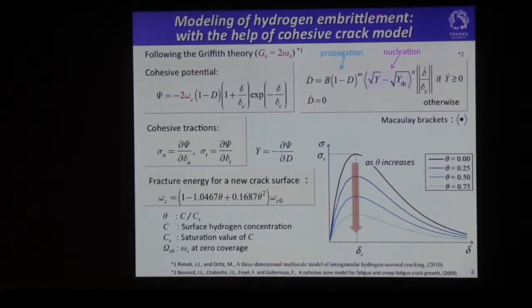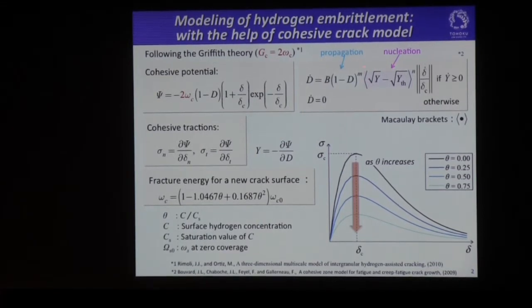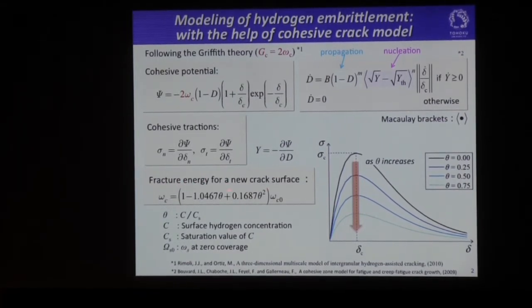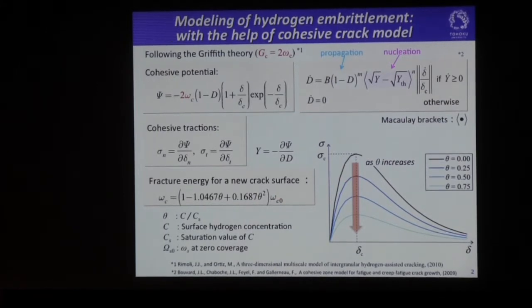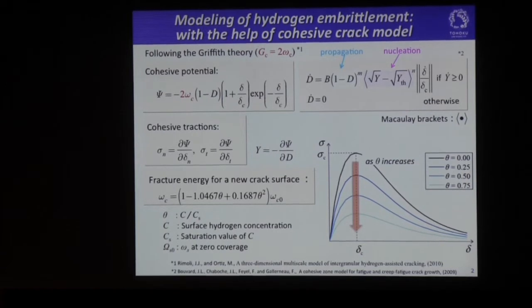This slide shows the modeling of the hydrogen embrittlement with the help of the cohesive crack model. Following the Griffith theory, I introduced the cohesive potential of this form. With this cohesive potential, we could derive the cohesive traction like this as a thermodynamic force. Here D is the damage parameter, whose evolution equation is given here, which represents the nucleation and propagation of the cracks. At the same time, this potential is multiplied by the fracture energy, which is a function of the hydrogen concentration. This is the relationship for the fracture energy for a new crack surface, which represents the reduction of the cohesive force as the hydrogen concentration is increased, as shown in this figure. This figure shows the relationship between the crack opening and the cohesive force.